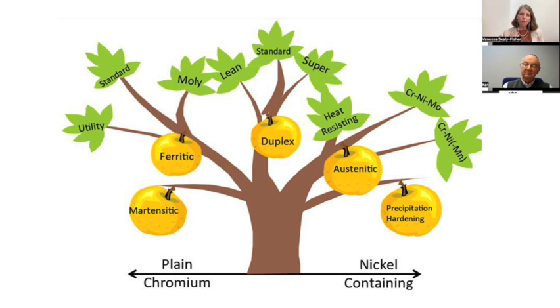Ken, what about fabrication challenges, welding issues? I know one of the challenges that are often raised from a site perspective is, but it's too difficult to weld. Or is that something that we also experience with duplex stainless steels? So again, I think let's just start by benchmarking against the 304, 316 materials, which are the workhorses in the austenitic range, which most people might be familiar with. So if we benchmark against that to start off with, I think what I can say is that the welding and fabrication is different, but not more difficult. Let's start off with that in mind. Different, but not more difficult.